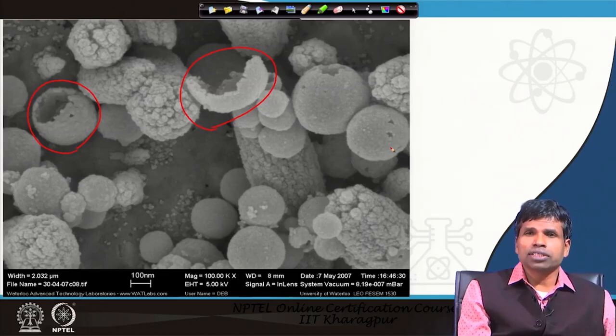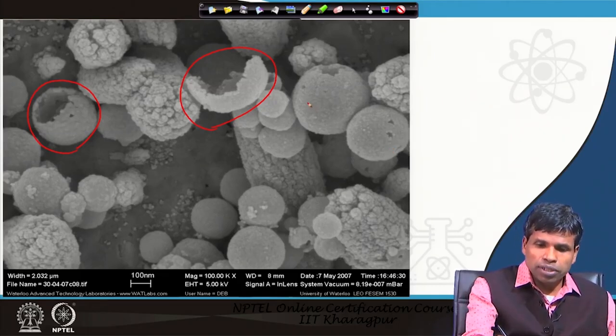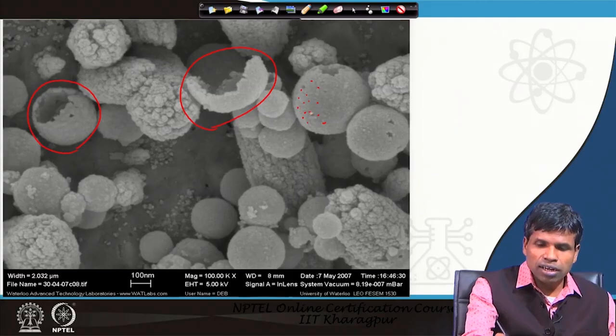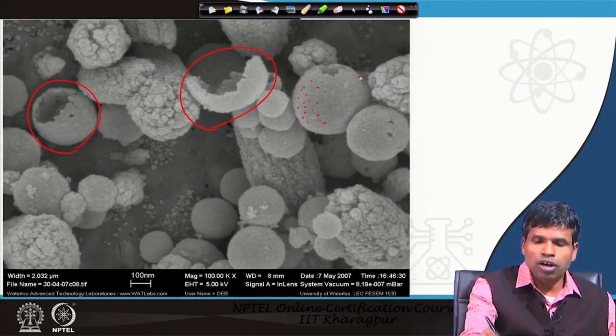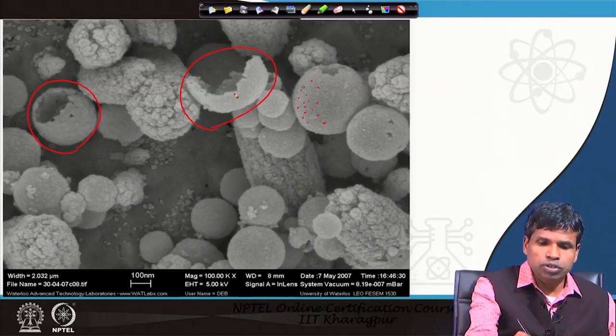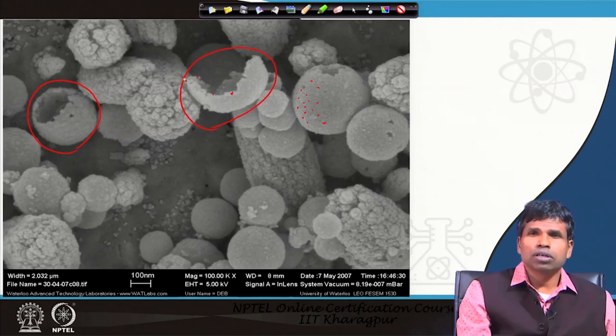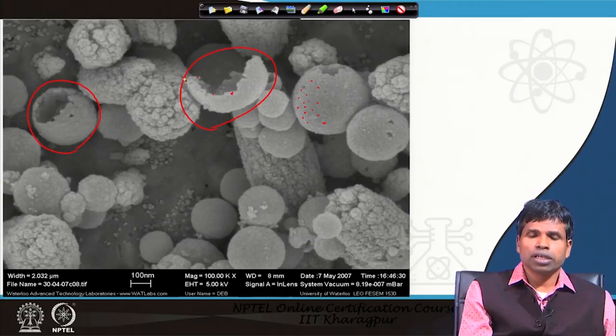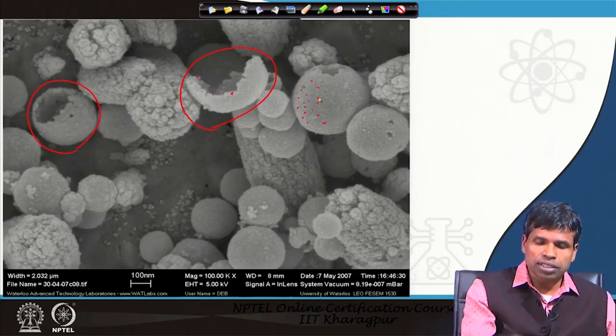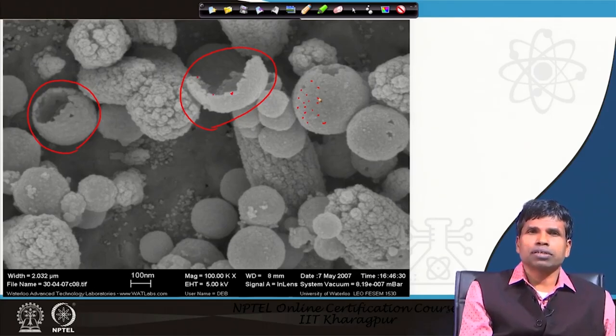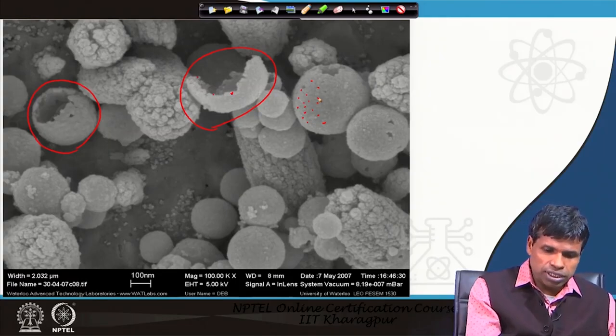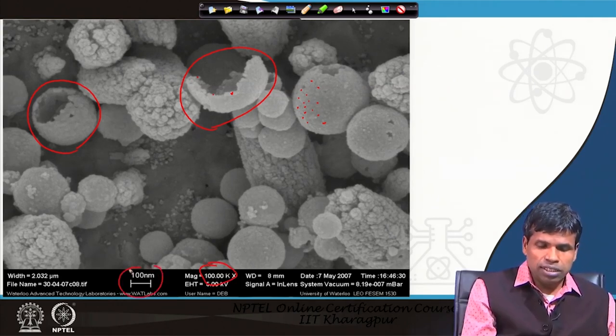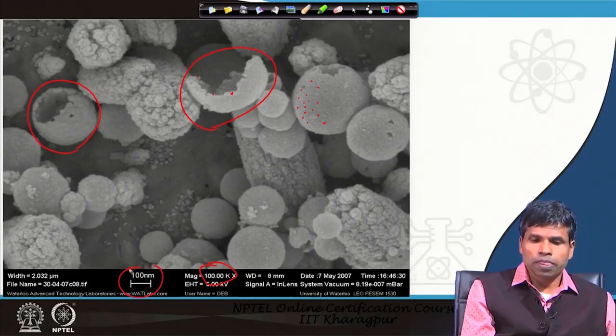Additionally, each individual sphere is formed from very small fine particles, visible as small bright dots. These spheres are self-assembled from very fine particles of size less than 5 nanometers. The distance between two of those white dots or particles is less than 1 nanometer. Here, the magnification is 100 kx and the scale bar has been increased to 100 nanometers.